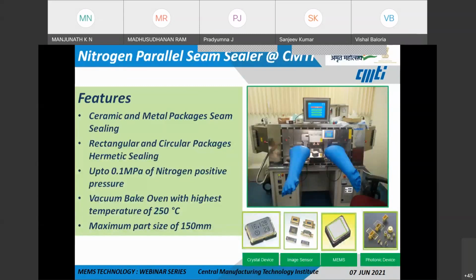And coming to the nitrogen seam sealer at CMTI, they usually have ceramic and metal package seam sealing applications. Both rectangular and circular packages can be welded, and up to 0.1 MPa of nitrogen positive pressure can be maintained within the chamber. There is also an attachment with a vacuum bake oven, which can reach up to 250 degrees centigrade. The maximum part size which can be seam sealed here is 150 mm. Crystal devices, image sensors, MEMS devices and photonics devices can be welded here.